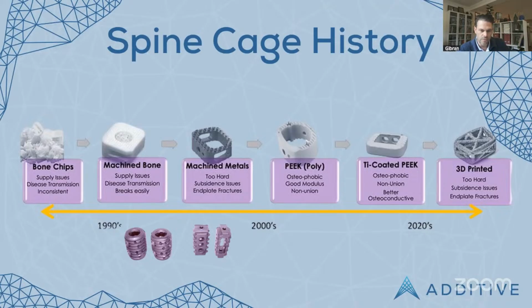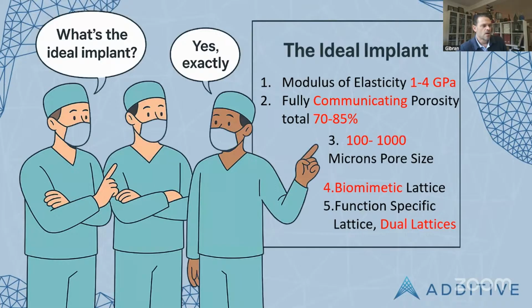And what we can see in this next slide is we got together to talk about what's important from a clinician perspective for their patients. What are we aiming for? What would the ideal implant look like? Some of the metrics that came up in these conversations, which led to our deep research and development, were that the modulus of elasticity needs to be around 1 to 4 GPa, that of bone. We want the porosity in the cage to be fully communicating, with all of the pores connecting to allow bone to grow on and through the cage, which in a lot of the 3D printed titanium implants at the moment is not the case; they're not fully interconnected pores.